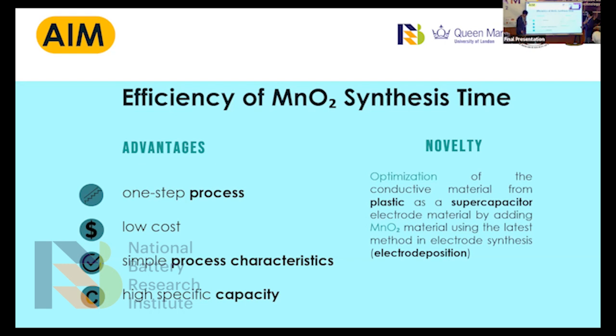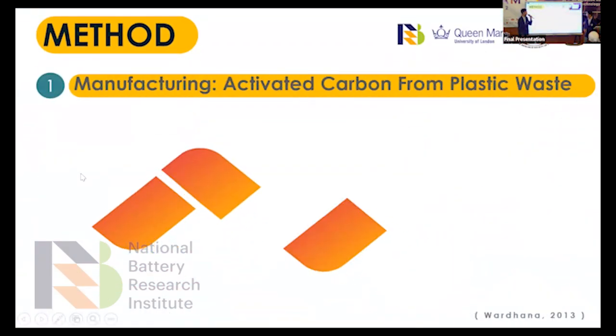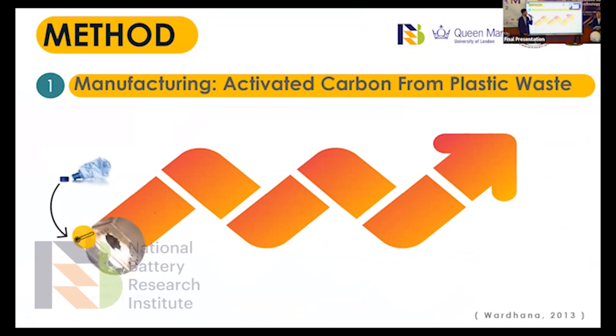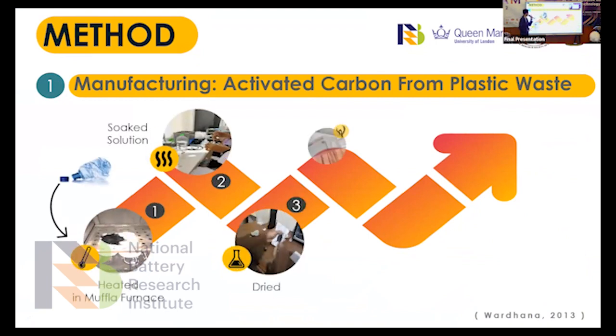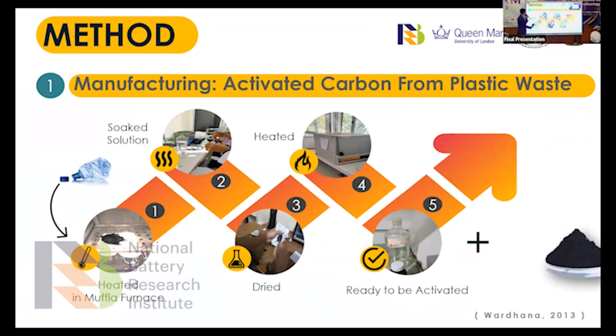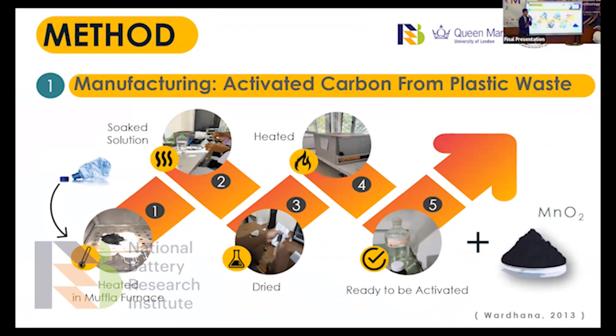So our novelty is optimization of the conductive material from plastic as a supercapacitor electrode material by adding manganese dioxide with the electrodeposition method. For the method, first we activate carbon produced from the polyethylene plastic waste. First it is heated in a furnace, then immersed in acetone for 24 hours and dried. The activated carbon is then used in the electrodeposition method.